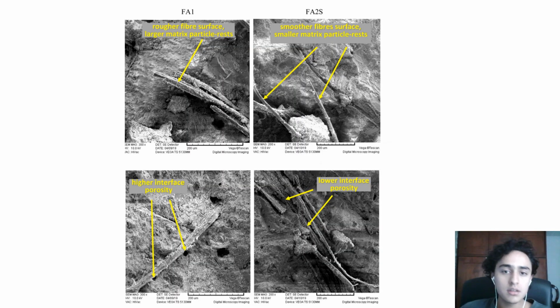In this electron microscope image, you can see the comparison of the matrix of both samples. You can see how the FA2S sample has a better interface, with less porosity due to the thinner fibers.